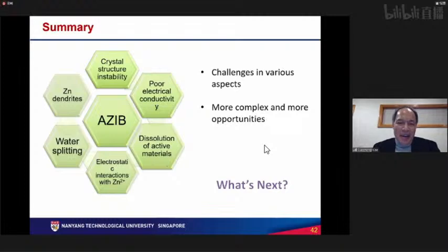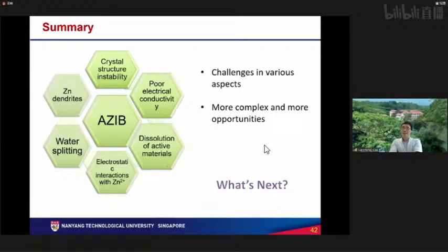When you mention those manganese-based cathodes that can give you a much higher energy density, what I know is that manganese-based cathodes give you a serious dissolution issue. Yeah, exactly. And that compromises the cycling stability. Exactly. That's why manganese oxide may involve phase transitions, or as I said, it can just dissolve into the electrolyte. That is why in the early days, people could get capacity much higher than the theoretical values, and people didn't understand how. It's actually exactly because of the dissolution reaction into the electrolyte. You can also see the solution may have some color. So later on, people tried to turn these disadvantages into advantages, and to broaden the voltage.